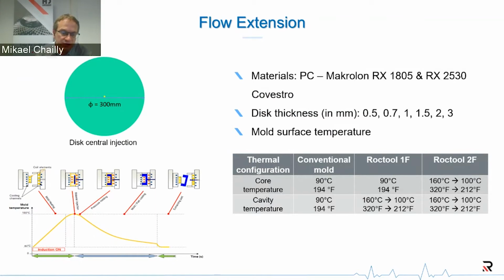And we tend to inject whenever we get the best thermal homogeneity on the molding surface, so to have the best results in the end. So when we talk about those 160 degrees C down to 100 degrees C, we are basically doing only cooling all the time while the material has entered the mold. If we switch to the next slide.